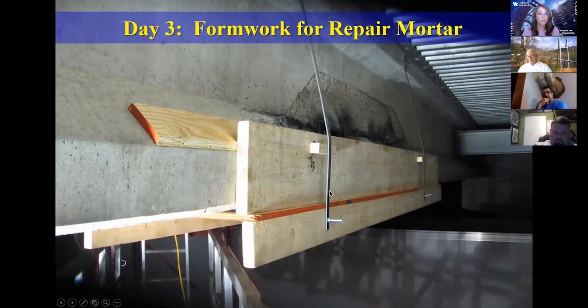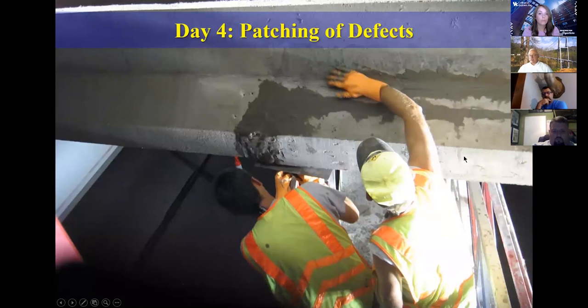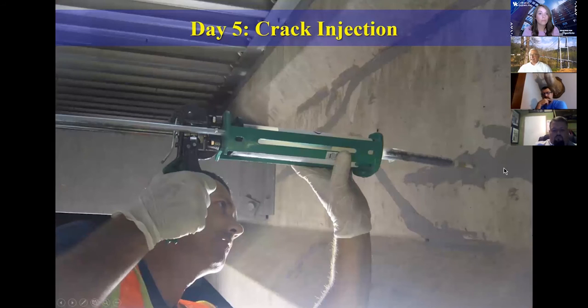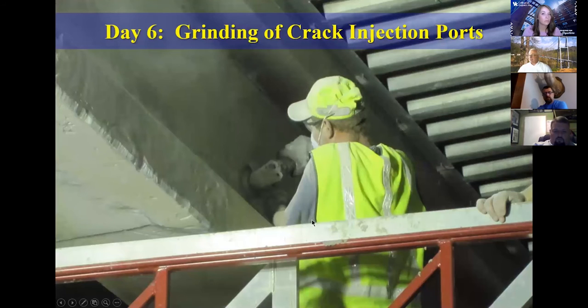After we did all the repair, we filled the concrete back to bring it to the original shape. And of course, there are going to be areas that did not fill properly, so we come back and patch these. And then we fill the cracks. We grind the surface to make it very smooth, so the bonding of the resin and the fiber to the concrete is perfect. We want the failure to occur inside the concrete and not at the bond region.